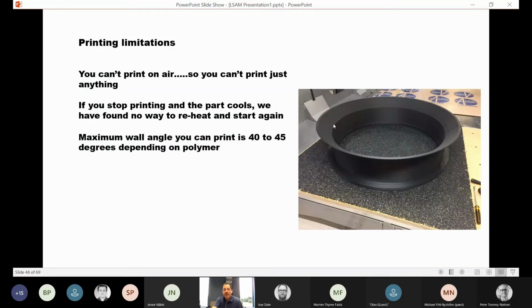There are, of course, some limitations. You can't just print on air, and you can't print just anything. If you stop printing and the part cools, we have found no way to reheat and start that print again. The maximum wall angle you can print is between 40 and 45 degrees, depending on the polymer being printed.